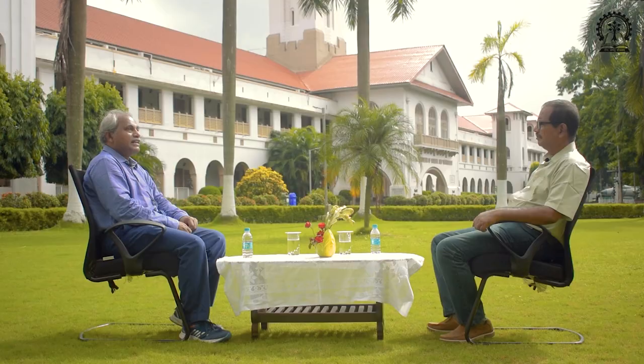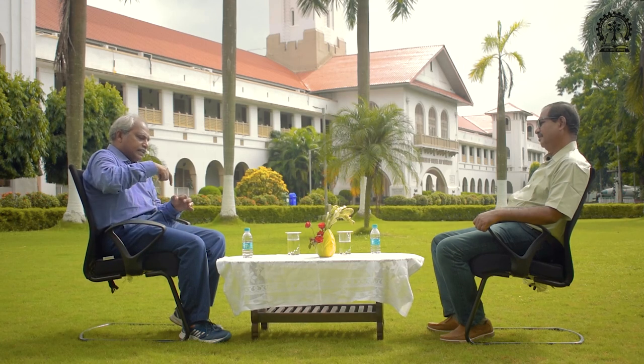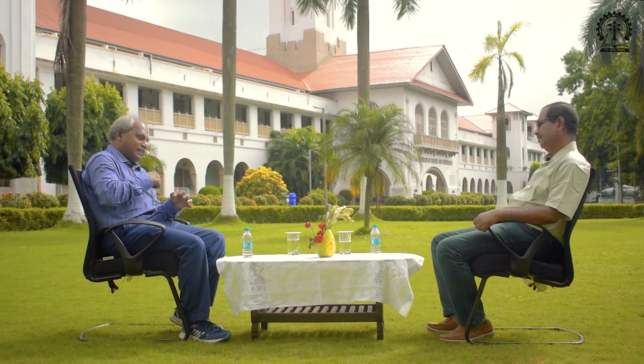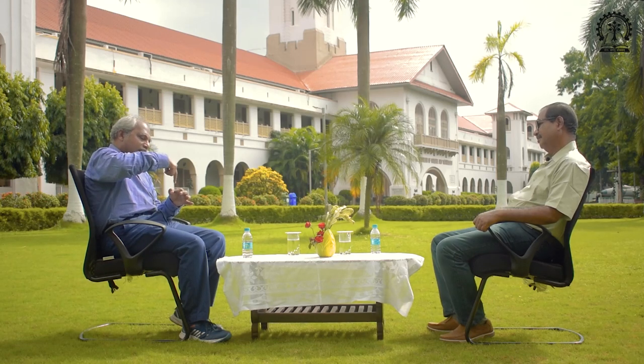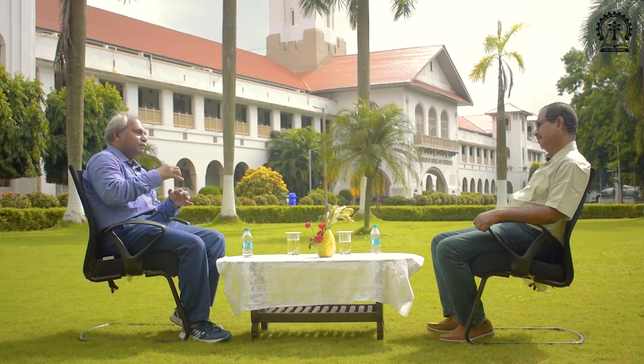Then we started to think how to prepare it in a very low cost, cost effective way. That time we used two disposable syringes, and the main body is called the spinneret, through which the spinning is done. The spinneret is a very simple assembly. There are two needles, one bigger, one smaller. The smaller needle is in the middle, and through the annular region, the polymer is allowed to flow. The polymer solution is made in a solvent, and water is an anti-solvent to the polymer. Whenever water comes in contact with the polymer, there is a phase change. The polymer gets solidified. It no longer stays a liquid. It becomes a solid.